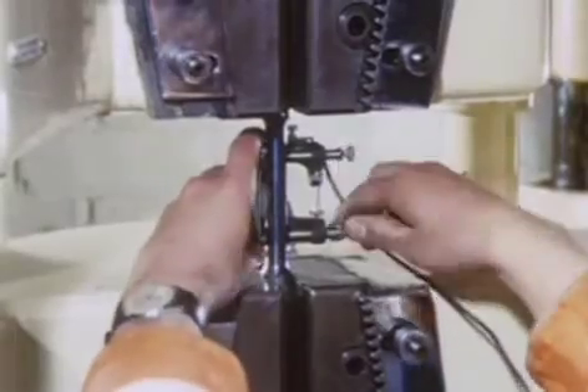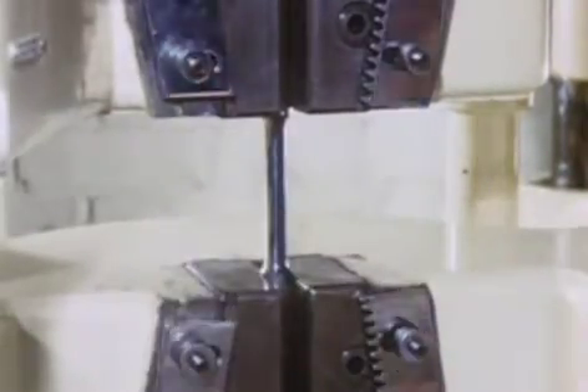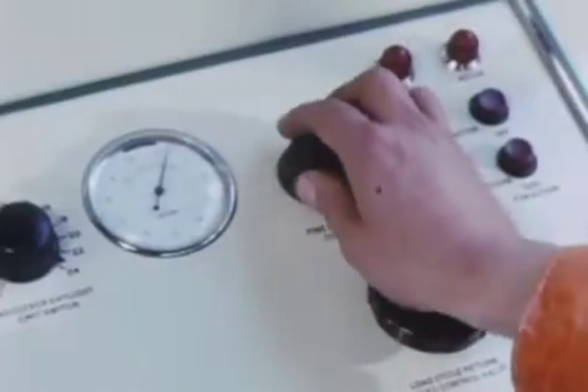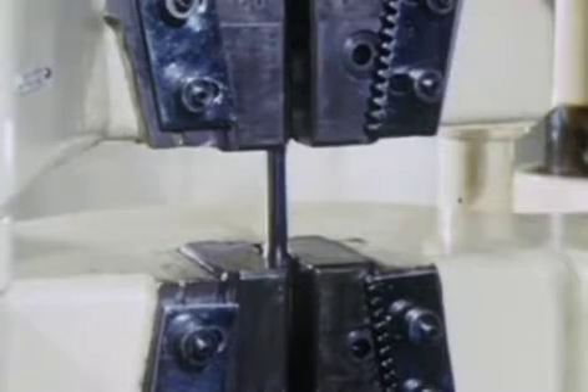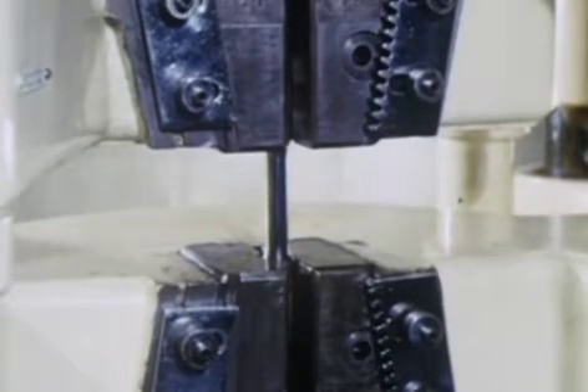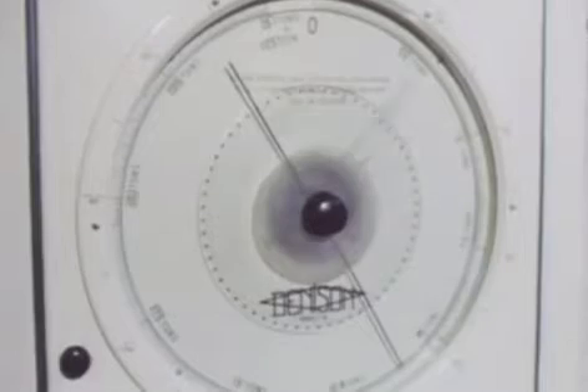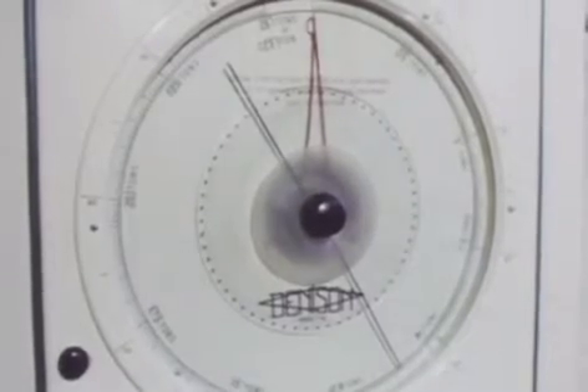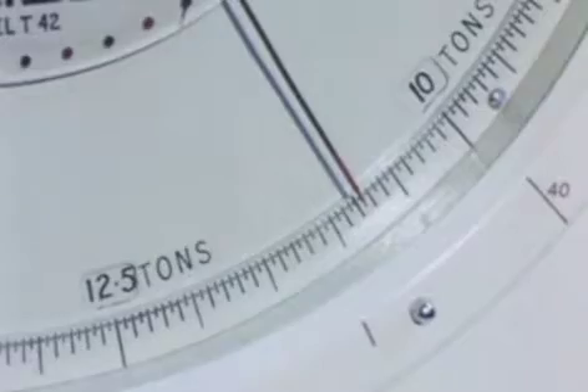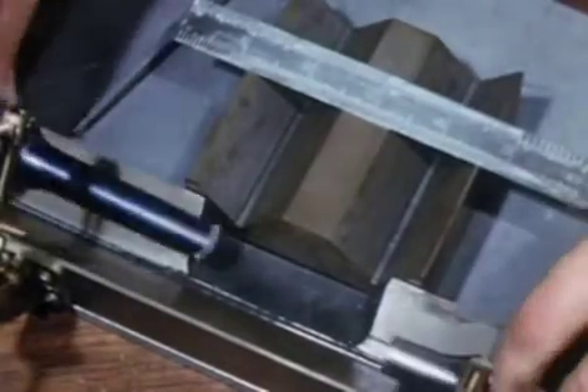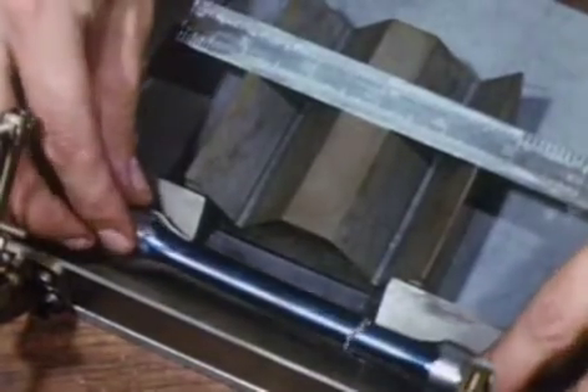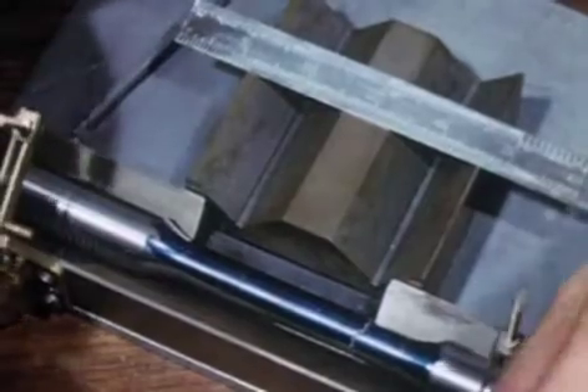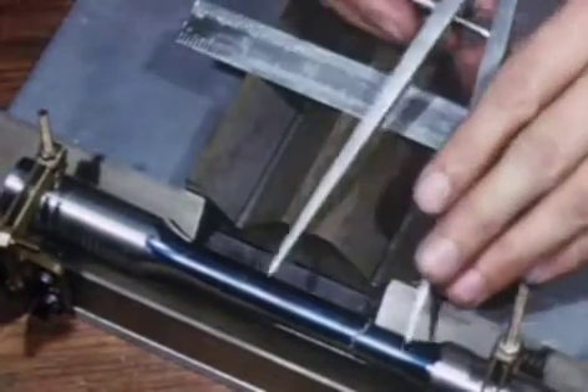The extensometer is removed from the specimen and then a further load is applied until the metal fractures. The reading on the machine, 10 tons, is the equivalent of 40 tons per square inch. The fracture specimen is reassembled in the clamp. Notice the degree of stretch which has taken place between the standard markings.